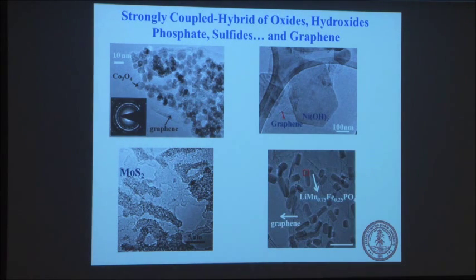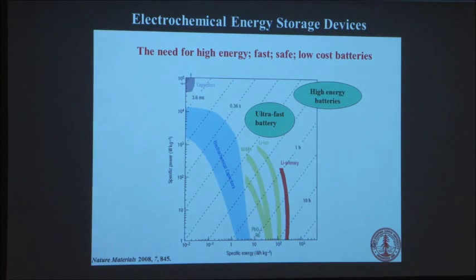We can make nanorods. Okay, these are lithium manganese iron phosphate nanorods on graphene. And if you don't grow them on graphene, they would make a lot of huge particles, okay, which would give you less good performance. So I'm sure you know a lot about batteries. A lot of excellent work is done here in Linda Nazar's group, for example, and a lot of other groups.